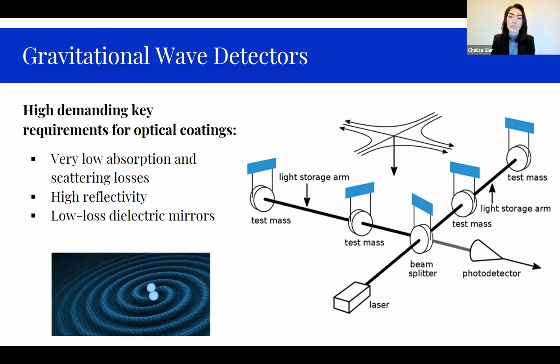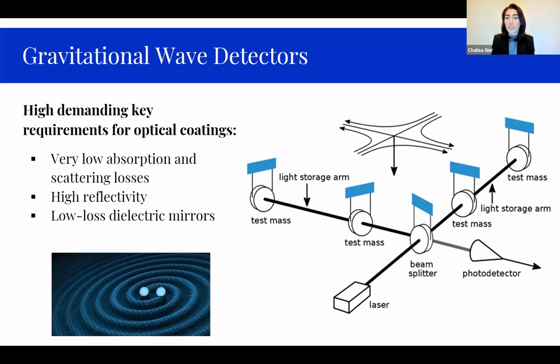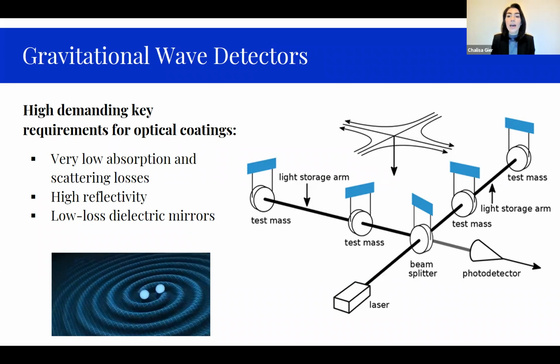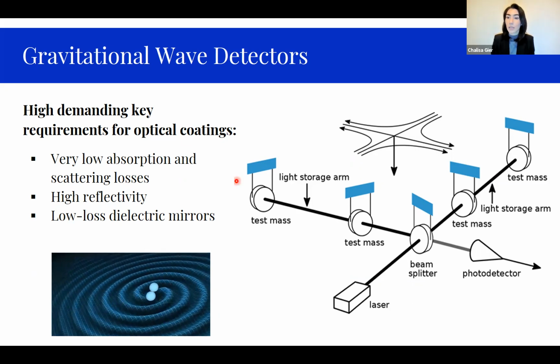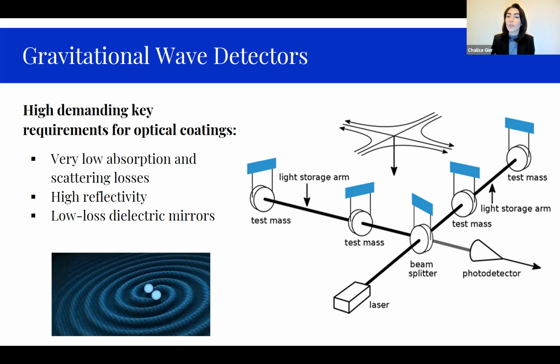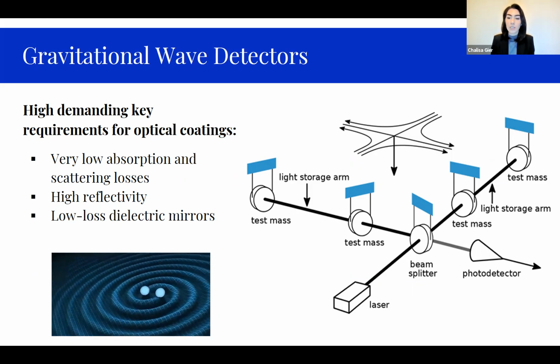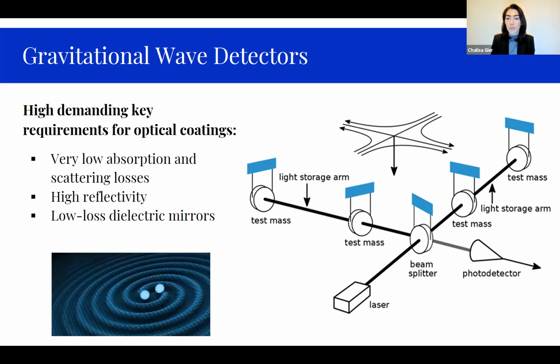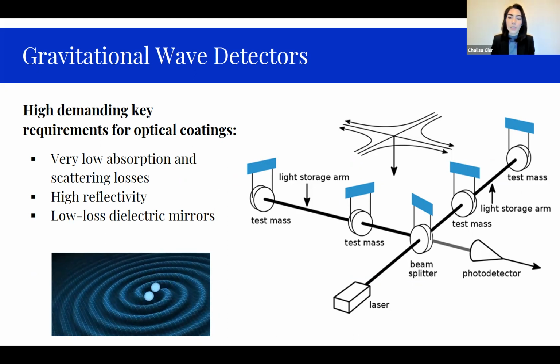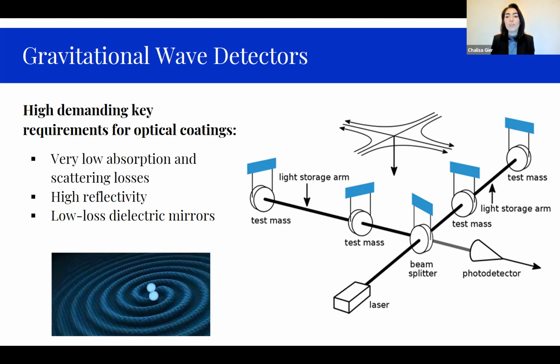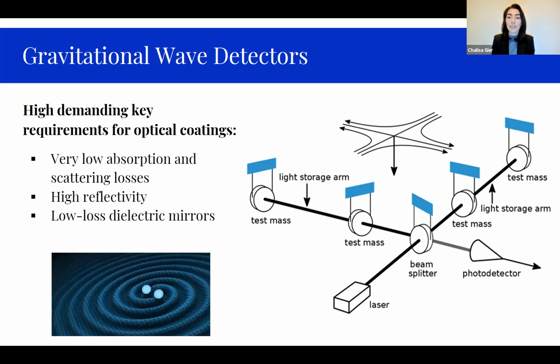The LIGO detectors utilize Michelson interferometer and Fabry-Perot cavity techniques. There is a highly demanding key requirement for the coatings on the test masses or the LIGO mirrors, which are very low absorption and scattering losses, high reflectivity, and low loss dielectric mirrors. And currently, the coatings that are being used at the moment are not reaching these requirements when fabricated by the typical commercial system.